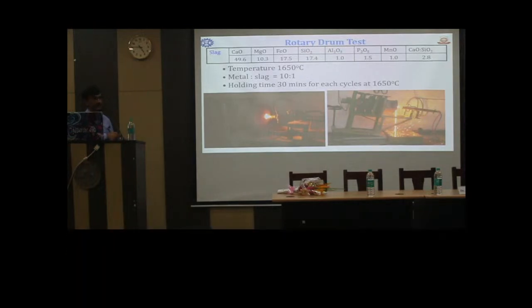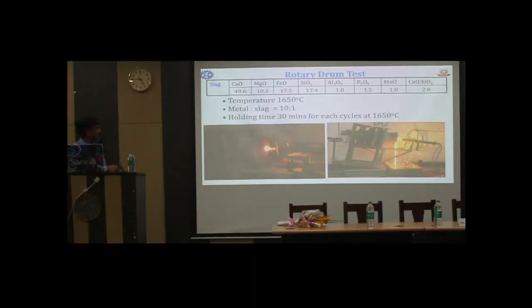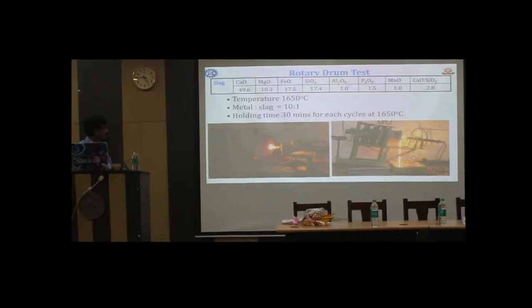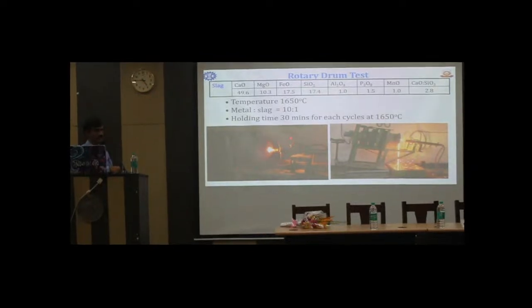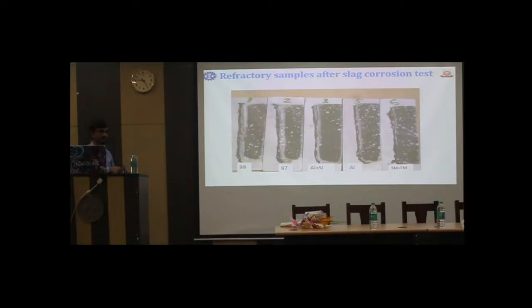So this is the rotary drum test. As I mentioned, small bars are lined inside the drum, and this drum is rotated at a particular slow speed with some angle. You use an oxy-LPG flame and melt the steel and slag at a particular temperature, maybe 1650 to 1680 degrees centigrade, and the ratio is 10:1. This is a standard test. After a few cycles, maybe 6 cycles, you open it, mount it in plaster of Paris and cut it, and then you can measure the area, how much it has corroded. Then you can compare the result with a standard one.